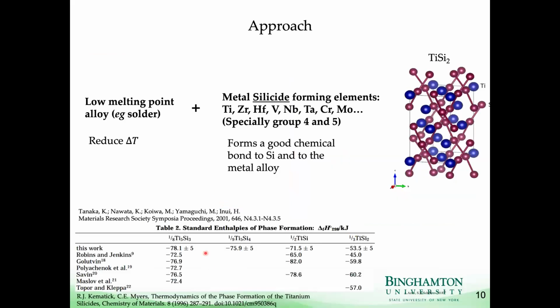So our approach to try to print metals onto silicon is to first use a low melting point solder alloy. This is to reduce the driving temperature difference for thermal expansion mismatches. The thermal stress is going to be a function of not just the mismatch, but also the driving temperature difference of that mismatch. So if we can use a low melting point alloy, that'll reduce the thermal stresses. And then to that solder, we want to add an element that'll form a reactive bond to silicon and form a particular silicide. So we chose to use titanium mixed with tin silver. It's like a tin silver lead-free solder plus some titanium.